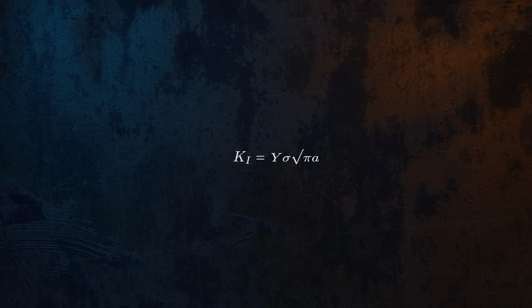The stress intensity factor is really useful because it gives us a single calculated value we can use to predict failure in real structures by comparing it against a material property. That material property, called fracture toughness, is the critical value of K at which cracks will begin to propagate within the material. It represents the material's resistance to crack propagation and is obtained experimentally using a standardized test.